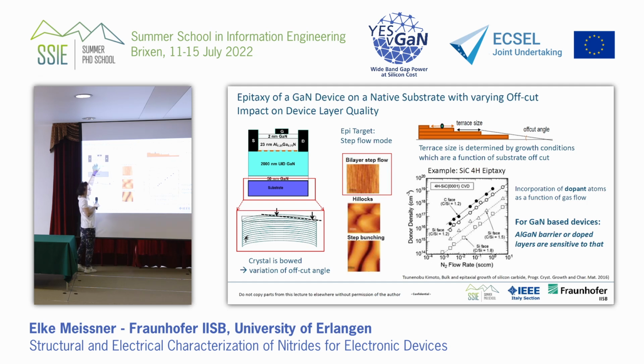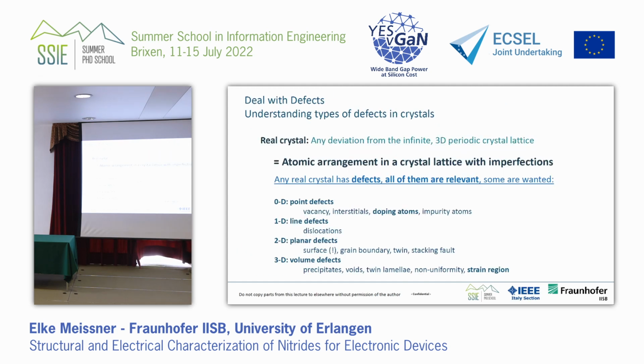And the same happens with the AlGaN barrier. Over the varying offcuts and the varying terrace sizes during epitaxy, the system will respond with different aluminum gallium nitride compositions. So also the composition of your barrier for a HEMT device will vary all over the surface area, which is also not what you want. Sorry for having switched these two transparencies.